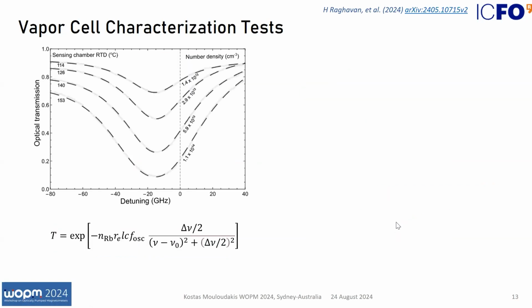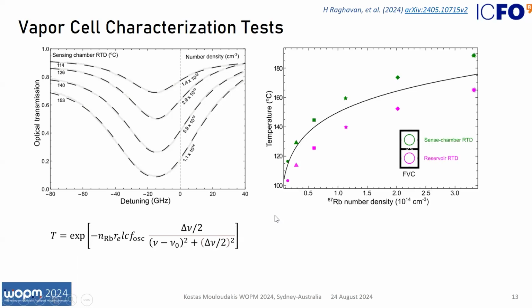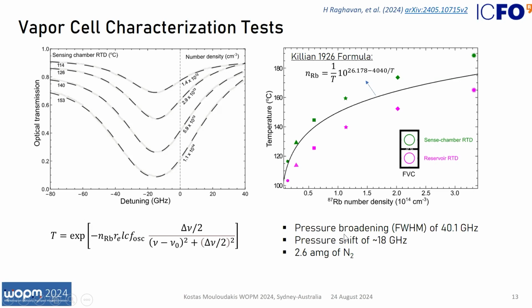Since we have calibrated our temperature sensors, we perform some characterizations on the cells. We perform absorption spectroscopy by scanning the wavelength of our laser beam using linearly polarized light at different temperatures, and we fit the absorption spectra using this Beer-Lambert law with a Lorentzian broadened absorption cross-section. From the number density extracted from this fit, we associate two different temperatures, one coming from the reservoir RTD and the other from the sense chamber RTD. And this black line is the Killian formula, and we find good agreement with this theory. From these fits, we can also extract the pressure broadening, which was about 40 gigahertz, and the pressure shift was about 18 gigahertz, and this led to a number density of 2.6 amagat of nitrogen, or 3 bars at room temperature, roughly.